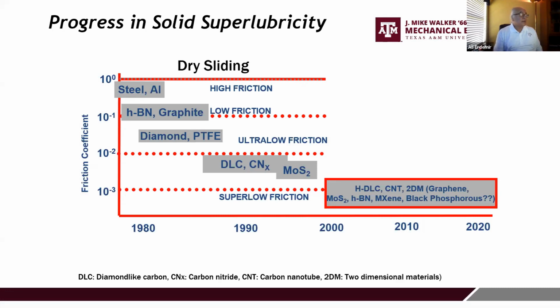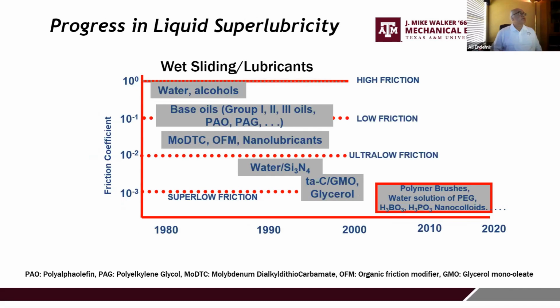But since the beginning of 2000, there has been an explosion in these kinds of studies, perfecting these 2D materials in a more controllable manner, and thereby, under the right conditions, even seeing levels of friction down to 0.001. These are quite remarkable, and I think that kind of shows us the way how sliding interfaces can be engineered or lubricated to achieve extremely low friction coefficients. And from a more practical point of view, of course, liquid